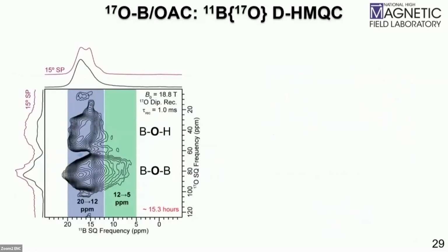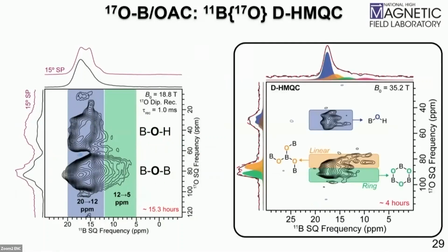We lastly then recorded these 2D boron-oxygen HMQC spectra, and here's one at 18.8 Tesla, and this took about 15.3 hours to acquire, where we start to get relatively good resolution where we can resolve the hydroxyl groups from the bridging oxygen atoms. Now, we very recently recorded this 2D NMR spectrum at 35 Tesla, and this only took about 4 hours to acquire.